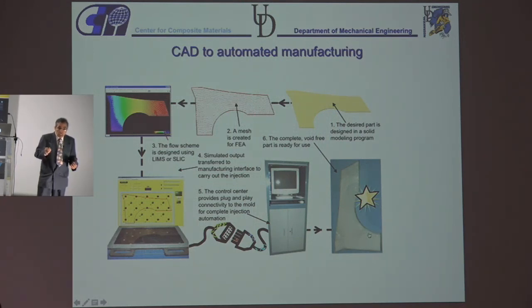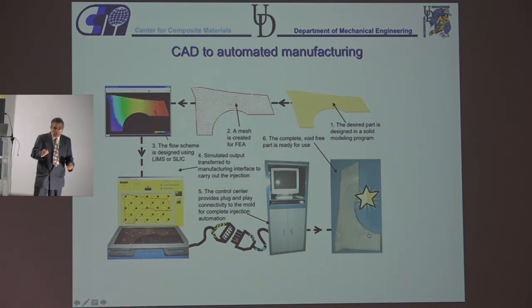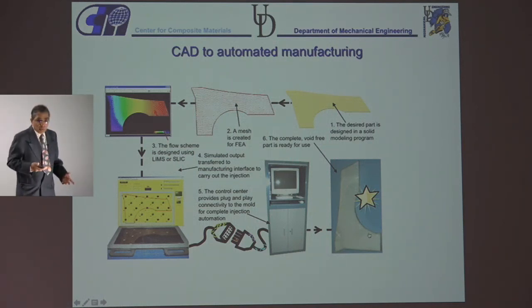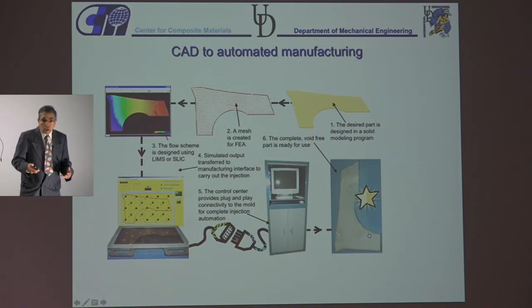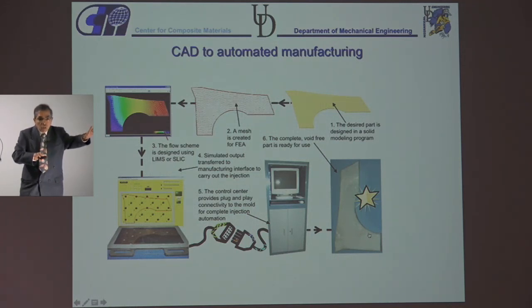It's possible because we can predict where the microvoids are, and then that information can be put into the same stress analysis for the platform, and you can do the stress analysis with those void locations to see if that void is going to be detrimental for your part or not. And for example, in injection molding, they do that in the sense that when the flow fronts come and meet, the fibers cannot go across the flow front, so you have a knit line. So they try to put the knit line in a place where it is not going to be structurally crucial. So you could do similar things over here too.